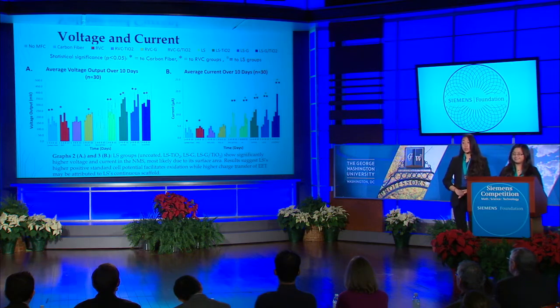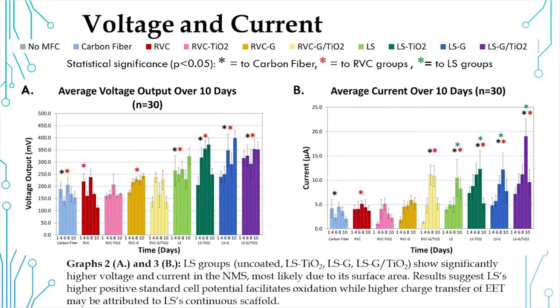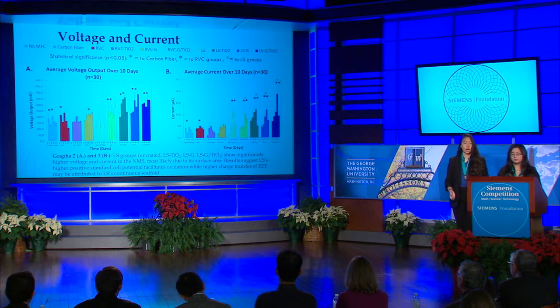The x-axis represents time in days, and the different colors represent the different anode designs. The y-axis represents the corresponding electrical output. Statistical significance with a p-value less than 0.05 is shown by the stars according to the key. For the voltage output graph, the loofah sponge graphene and the loofah sponge composite have significantly higher voltage output when compared to the carbon fiber and the RVC. Because the cathode was kept constant, the cell voltage was an indicator for anodic potential. So the higher anodic potential showed higher potential energy per unit charge.